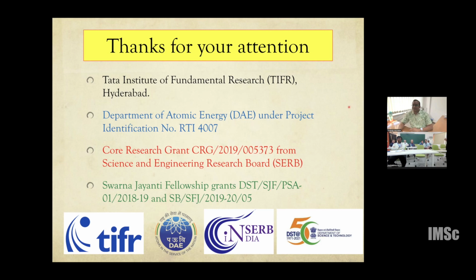Yeah, I had a question. For this, you are annealing in different directions, right? You are annealing by oscillatory shear, shearing it in different directions. Yes, oscillatory shear. What is the typical strain amplitude that you use to anneal them? This system that we studied has a yield strain at around 0.07, and we vary the strain amplitude from 0.01, 0.02, 0.03 up to 0.06. If you go beyond, then you do not get any annealing; you basically get yield.